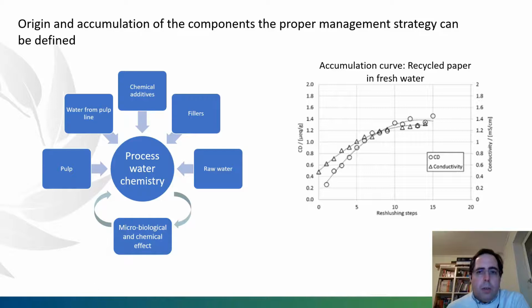And another thing that is very important is that there is a cumulative effect on the composition and the concentration of these contaminants. That means that when we reduce the water consumption, we will be in an exponential situation where any small change will have a dramatic effect on the composition, and therefore a dramatic effect on the efficiency of the chemical.